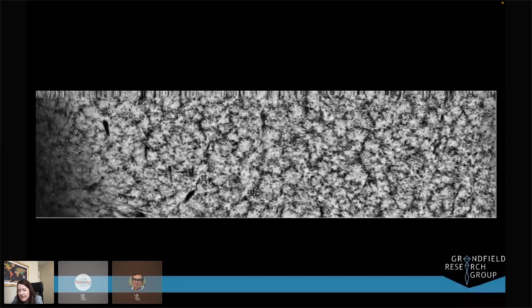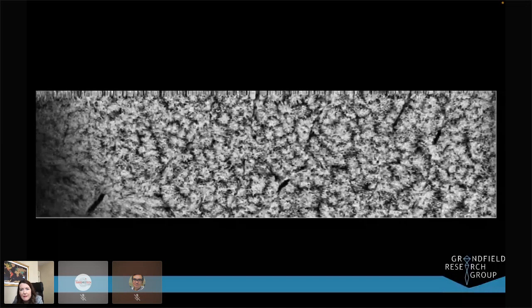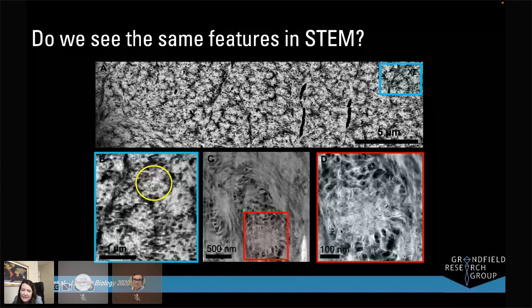We had seen these before, in a little bit of work at higher resolution. In the red images over here, we have some features we saw in the scanning transmission electron microscope. But with the plasma FIB, we can see these features are everywhere. The STEM, remember, was quite a small volume, so we didn't have a large area to look at. But with the plasma FIB, we see these features across a huge volume. The other exciting thing with the plasma FIB is we have a three-dimensional data set.